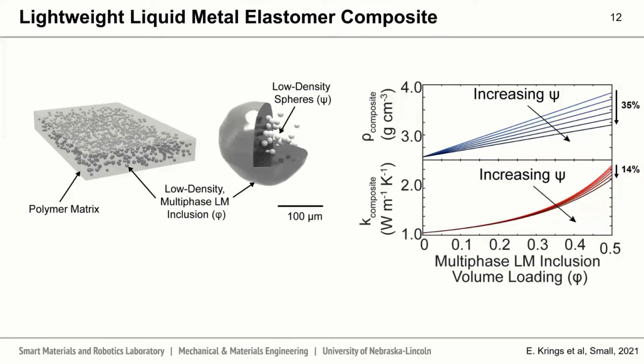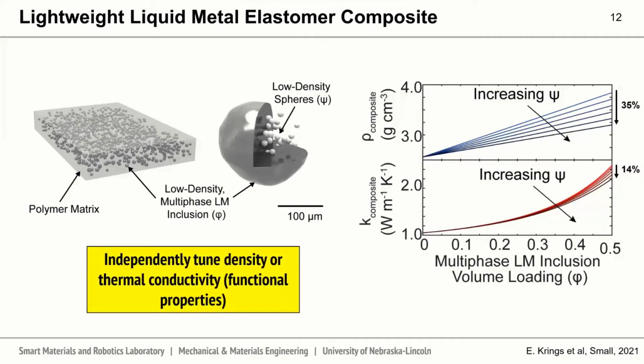What we see is as we increase the volume loading of these low density spheres within the liquid metal, we see an approximately 35% decrease in the density as we load them up to 50% by volume, and only a 14% decrease in its thermal conductivity. This nonlinear relationship allows us to independently tune the density or thermal conductivity or the functional properties of this composite.